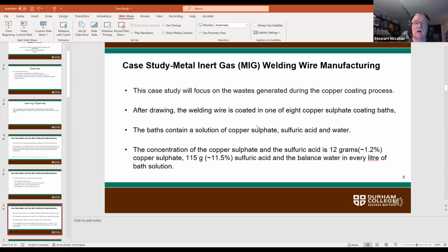The baths contain a solution of copper sulfate, sulfuric acid, and water. The concentration of the copper sulfate and the sulfuric acid is 12 grams, or approximately 1.2% copper sulfate, 115 grams, or approximately 11.5% sulfuric acid, and the balance water for every liter of the bath solution. So that's the type of information that you need to know. You don't need to know it so much in order to characterize the waste. You just need to know what's in the waste. But it's certainly needed to calculate your actual releases for the National Pollutant Release Inventory. These concentrations are the type of information that you need to have.